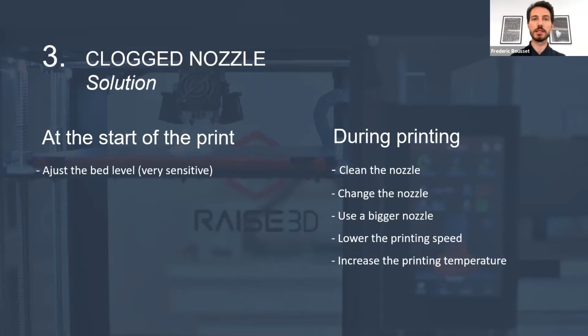For the guidelines that we give out, I think the printing speed should be around 10 to 20 millimeters per second. If you have some problems with the nozzle, you can go down to around 5 millimeters per second, I would say. This should help a lot. If it isn't enough, you can increase the printing temperature. For the H13, it is 180 to 200 degrees. You can go above, like 210, if you find it useful. I won't go over 215, because after that the surface quality of the part you have printed isn't good enough. So don't go over too much. Thank you, Fred.